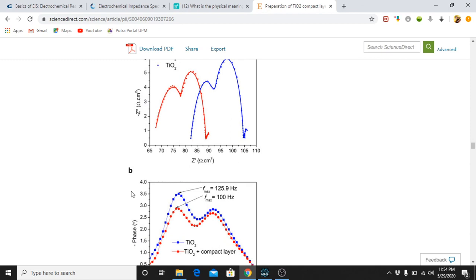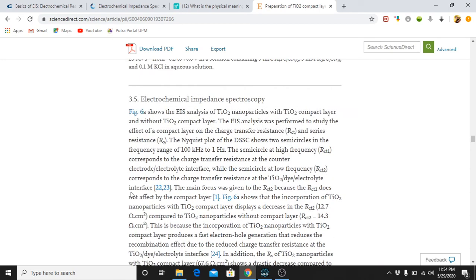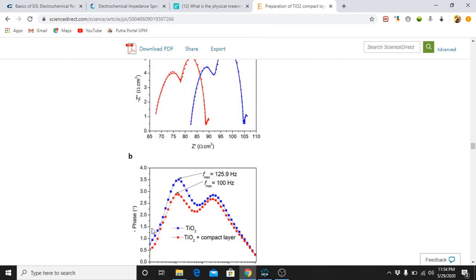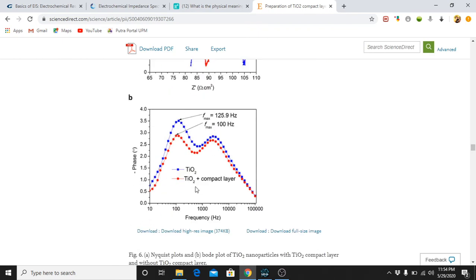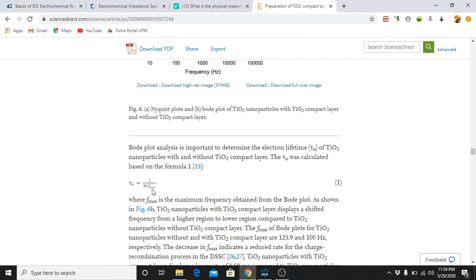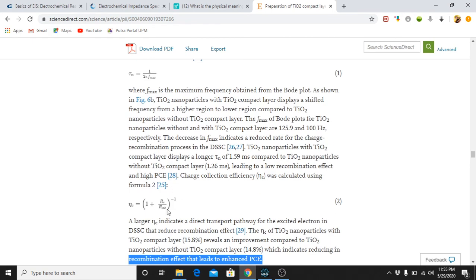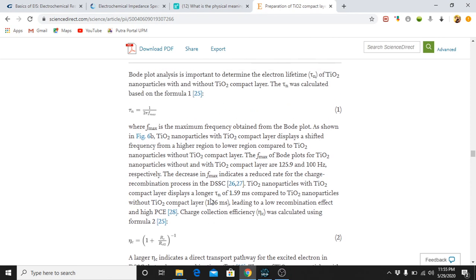When you are studying the compact layer in DSSC using impedance, we generally discuss the charge transfer resistance, the series resistance, and also the Fmax value. From these values, using the equation, we know the electron lifetime. We want a longer electron lifetime and a larger charge collection for enhanced power conversion efficiency. That's why, by having a compact layer, we can increase the power conversion efficiency: it reduces recombination, because the compact layer itself acts as a barrier, a passivation and blocking layer, to block the unnecessary recombination of electrons from the TCO with the redox electrolyte.